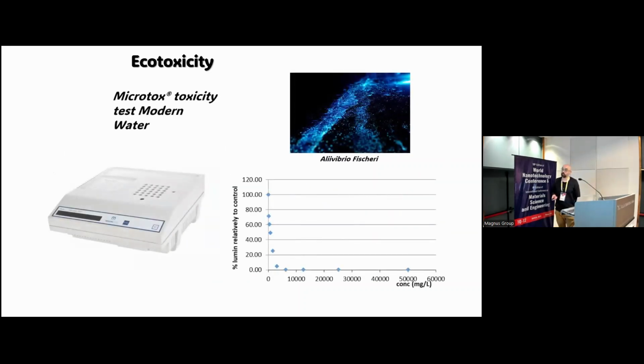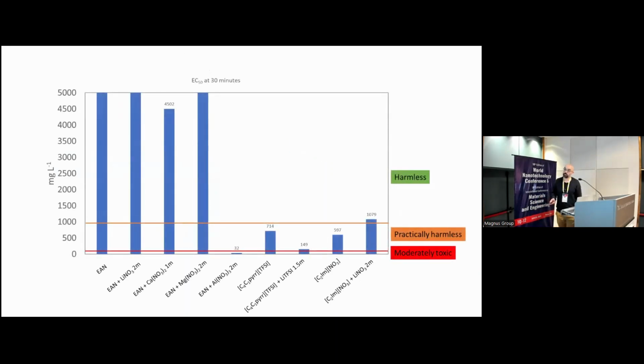We have also measured the ecotoxicity through a Microtox toxicity test with Aliivibrio fischeri, a bioluminescent bacteria. We can determine this toxicity through the luminescence relativity of this bacteria. You can see that this is the ethyl ammonium nitrate, the one I was talking about, and this is the mixture with lithium, calcium, magnesium, and aluminum. You can see here that this is the harmless part of the graph, and most of the mixtures fall in the harmless part. Just the case of aluminum is falling in the moderately toxic part.